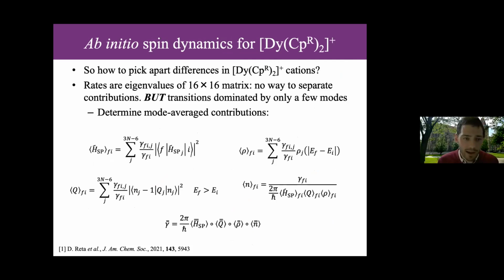And so here we're defining a set of new matrices. So these are each element, so there are 16 by 16 elements of each of these terms. Okay, so these are the different matrices. And each one is the sum over the 3n minus 6 vibrational modes of the gas phase. And what we do is we just take each of these individual terms. So we have the spin phonon coupling part, so that's the electronic matrix element.